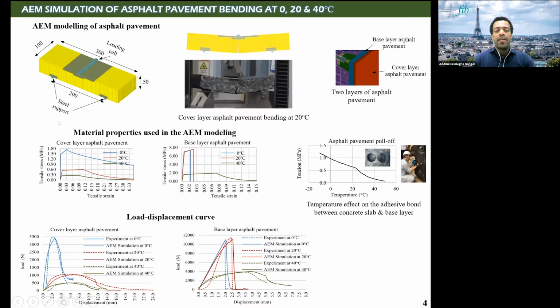We utilized the asphalt pavement. The constitutive model of the asphalt pavement is bilinear until the ultimate strength, then we show softening behavior in the numerical simulation as a material property of asphalt pavement. For example, this one is the cover layer asphalt pavement, tensile stress versus tensile strain. The blue one is at 0, the red one is at 20, and the last one is at 40 degrees centigrade. This one is the base layer asphalt pavement, tensile stress, tensile strain. And you can see at 0, at 20 and at 40 degrees centigrade.